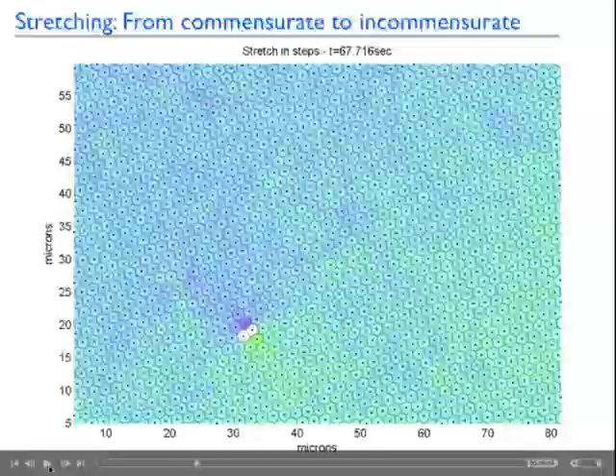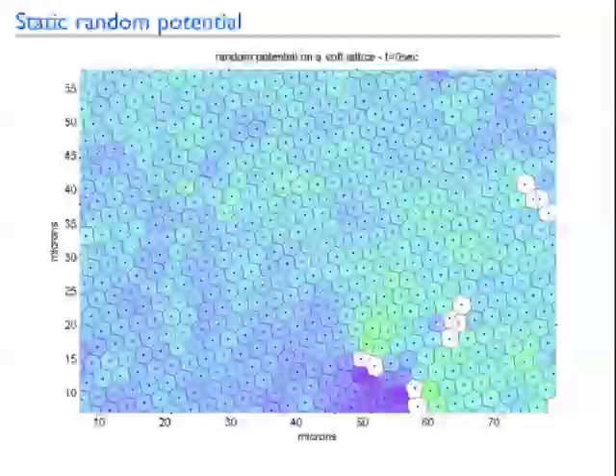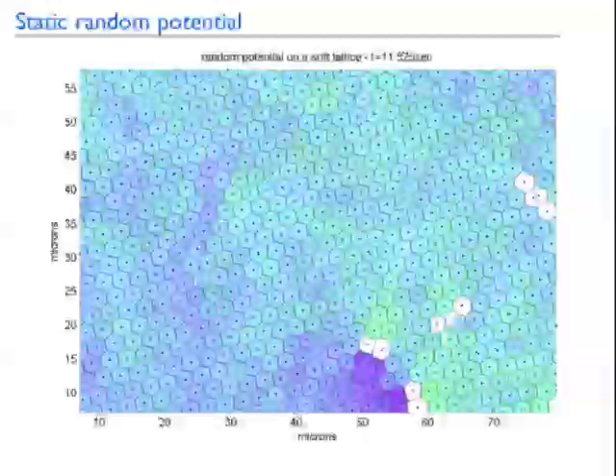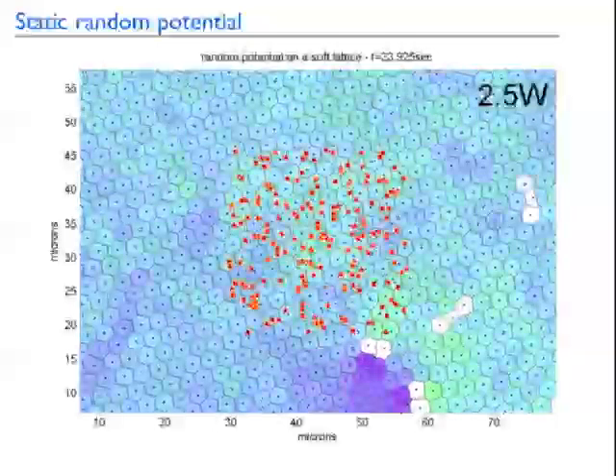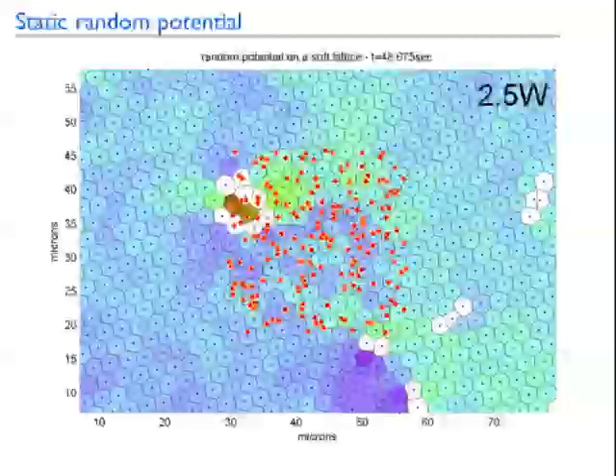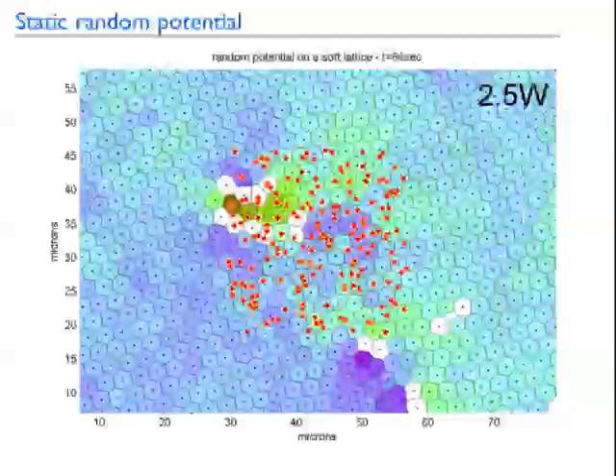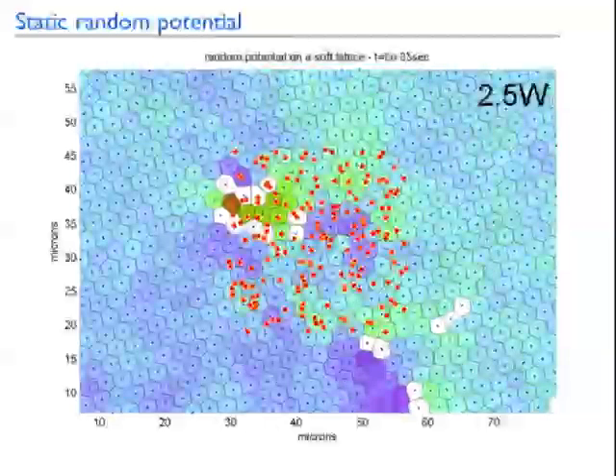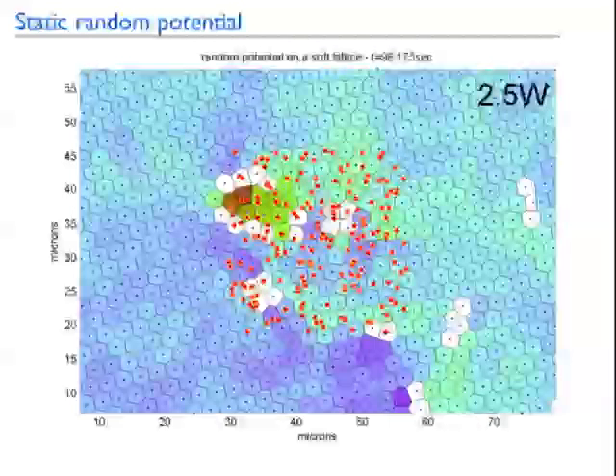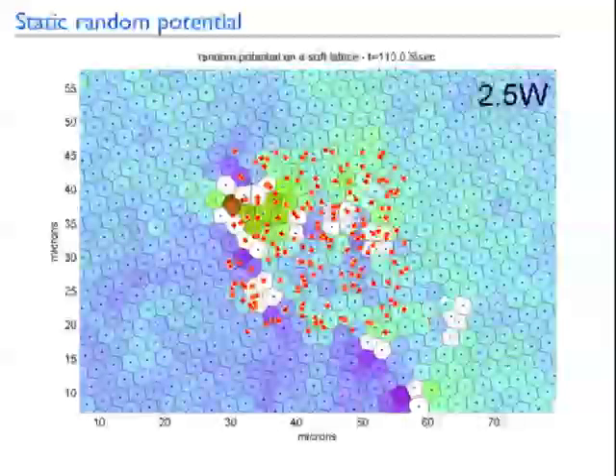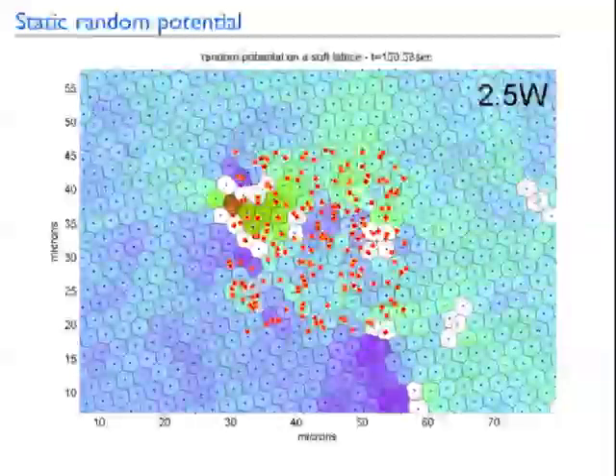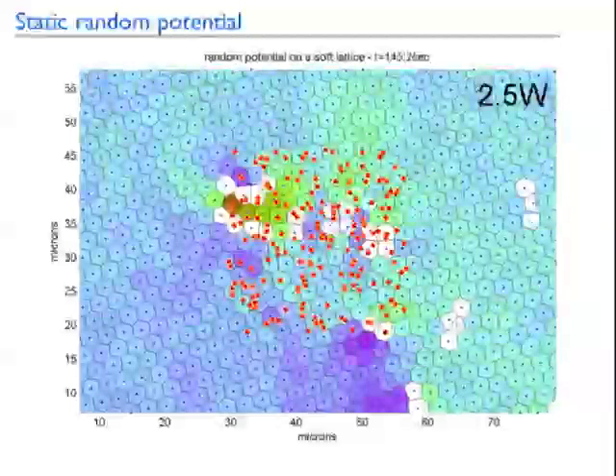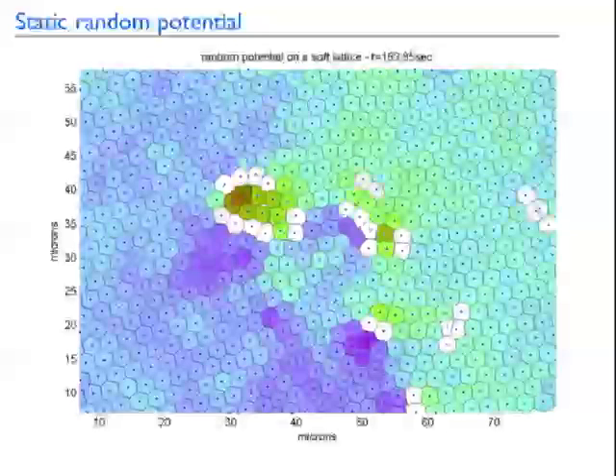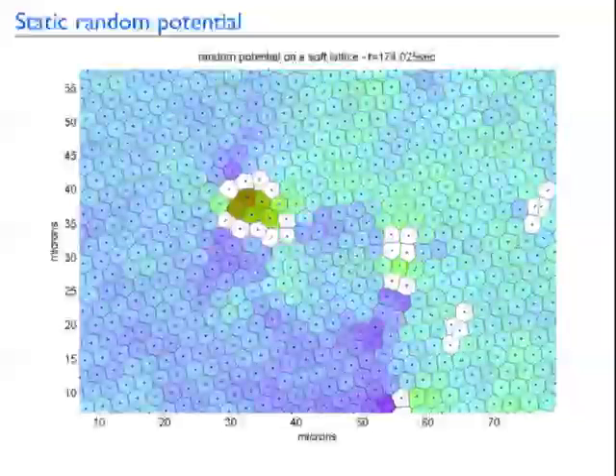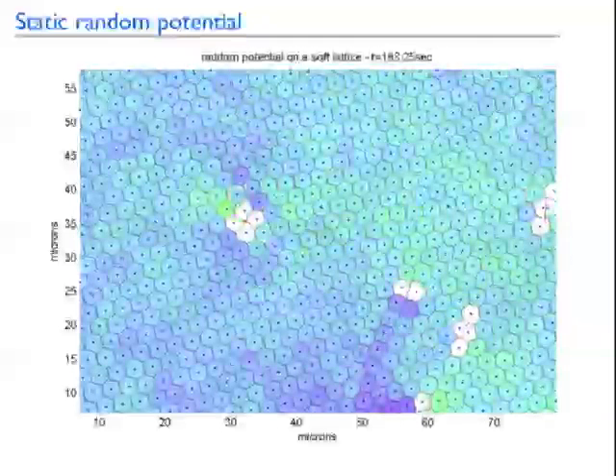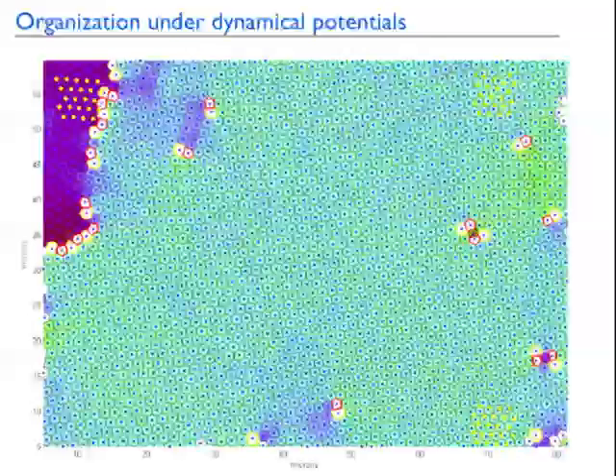Okay, so you can do that with this, and you can watch what happens to the lattice as you introduce disorder, in this case, a potential that's just put on by the optical tweezers. So those are very weak tweezers, and you can see that this lattice is breaking up. It's no longer perfect over here in the region here. It's breaking up into domains over here, okay, which are taking advantage as best they can of that disorder potential, right? And in studies that we're doing now, you can take this whole thing and put it in tweezers and see whether it's pinned or not, and watch the motion of it. And you turn it off, and they just heal, right? So there's lots of really interesting physics that happens with this.